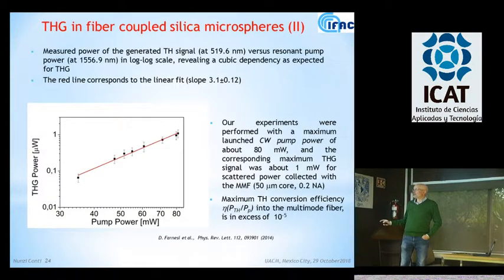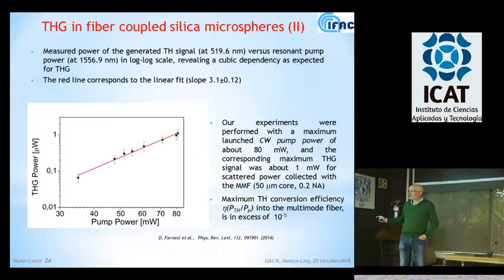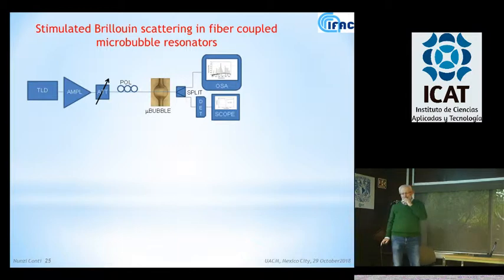This is the typical cubic dependency as expected for the third harmonic, so the slope is about 3. With 80 milliwatt, of course this is the launch power, we could get about 1 milliwatt of third harmonic collecting the scattered light, and through the fiber it was 1 order of magnitude lower, but still it was quite an efficient process. Again, this is because we could couple the right whispering gallery mode.